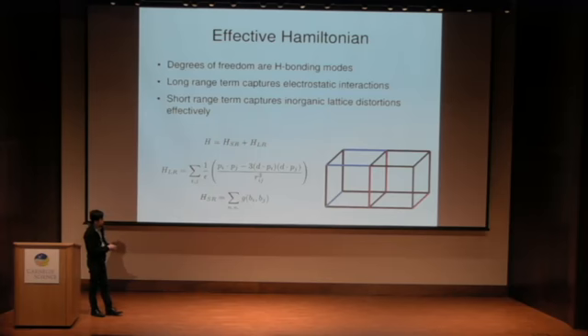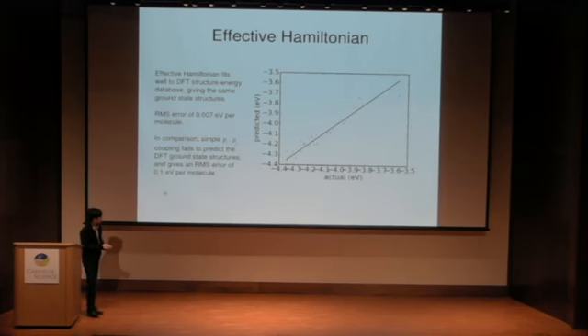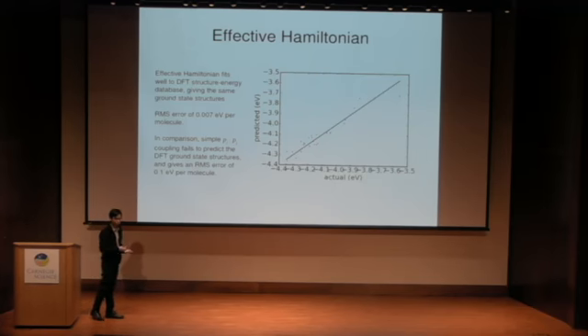And so I've implemented this model and fed it to my database. And I get a somewhat reasonable fit, I would say. So this is over the entire energy range of the database. And I would say that it correctly predicts what the ground state structure should be. So these points here are actually the orthorhombic low temperature phase, and that's predicted correctly by the model. And I achieve like 7 meV root mean square error. Now, if you compare this to a very naive model where you use a different coupling, like a dot product vector-like coupling, that kind of model fails miserably. You get a much larger RMS error, and even the ground state structure which is predicted is wrong.